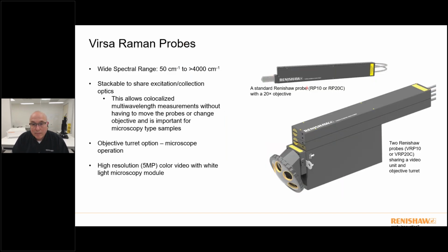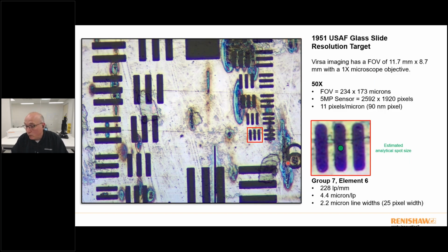So there's quite a lot of functionality with these type of tools. The Virsa probes themselves, amazingly, turn on at 50 wave number, so you get close to the laser line performance. And then the total spectral range is really dependent on the laser and the detector limits, but generally the filters will perform to better than 4,000 wave numbers. And they are stackable. So if you have multiple probes, you can stack them, and that allows you to share excitation optics. So you can have completely automatic laser selection in the software without having to physically change anything on the instrument. And that I feel is really unique. Like I said, you can have the objective turret in here, and then on the box itself, we have a 5 megapixel video camera with white light microscopy on there. And that actually does a really, really good job at being able to visualize the sample.